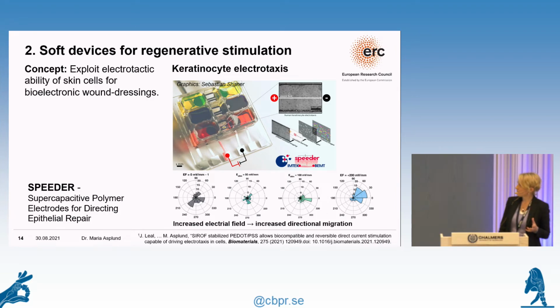So we have here some cell culture data. This is from single cells. So we can really see here when we increase the field strength. So here we have a 0 field, then we go to 50 millivolt per millimeter, and then up to 200 millivolt per millimeter. And this is a statistical graph showing the direction in which the cells move. And we can see at the higher field strength, more or less all cells move in the same direction.